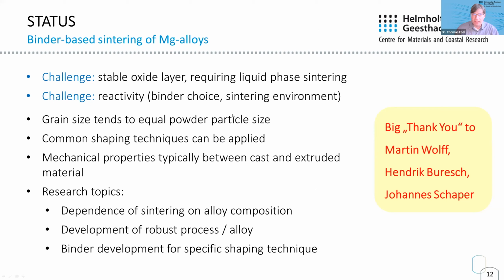Typically, at least if you use binder-based techniques, because you usually want to make rather small parts, you have something like a few centimeters. And because you have to remove the binder, the wall thickness shouldn't be too large. Let's say maximum 5 to 10 millimeters, if possible. It depends on the exact part, but you are usually speaking about smaller parts, and sintering always means that the part is shrinking, and these are things you have to consider.